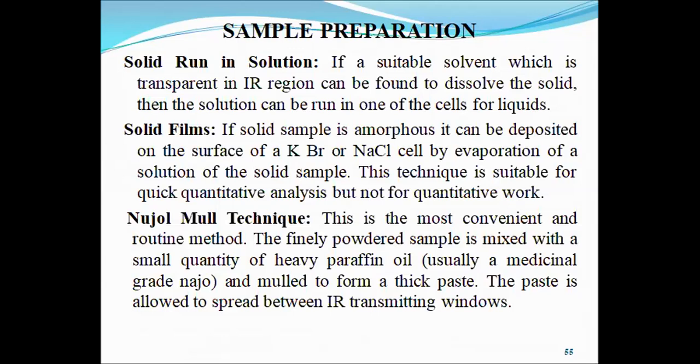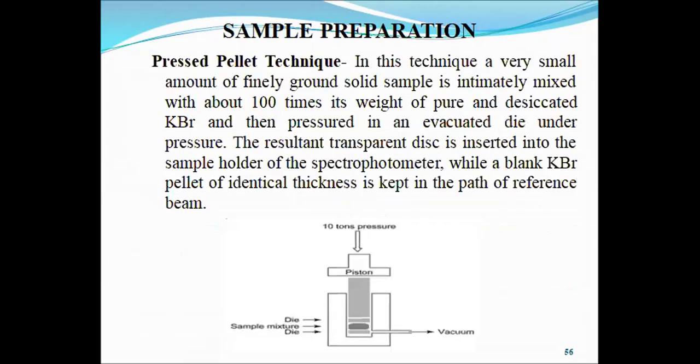The Nujol mull technique is the most common technique for sample preparation. Here the finely powdered sample is mixed with a small amount of paraffin oil, termed Nujol, and molded to form a thick paste. Therefore, it is termed the Nujol mull technique. The paste is then spread between the IR transmitting windows.